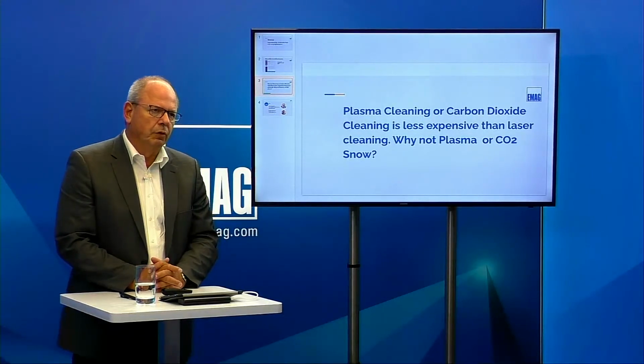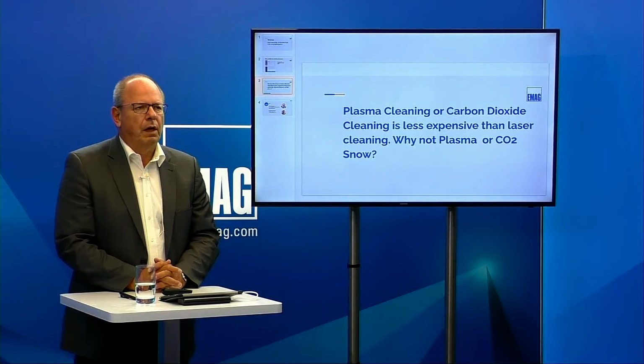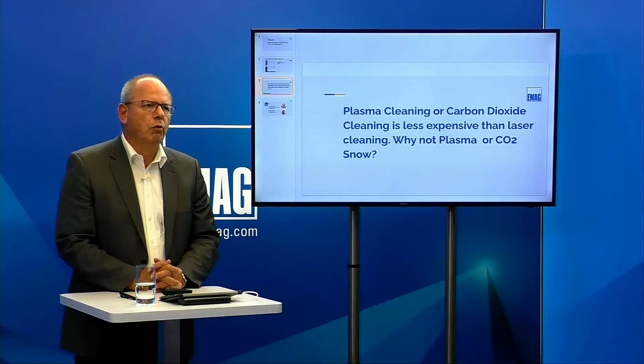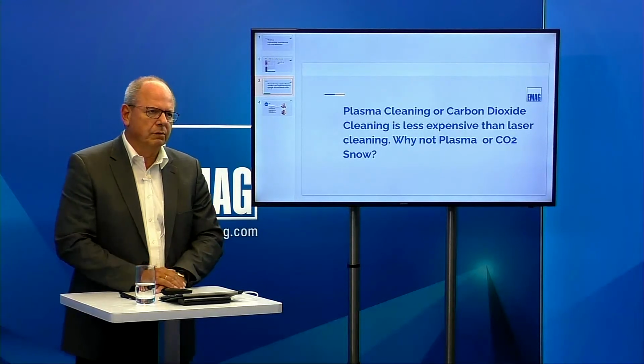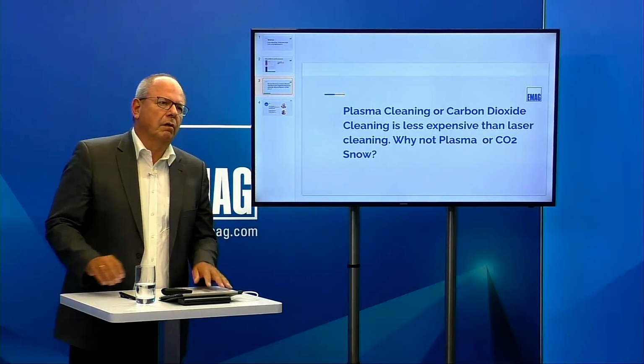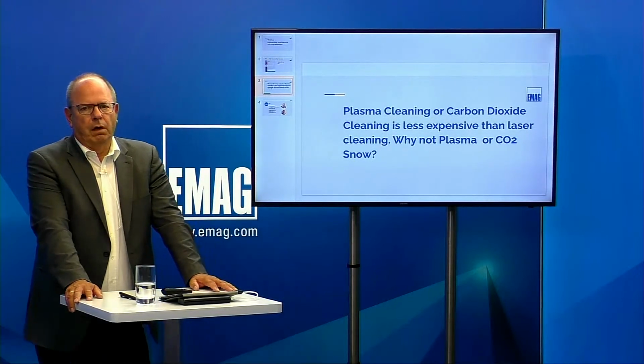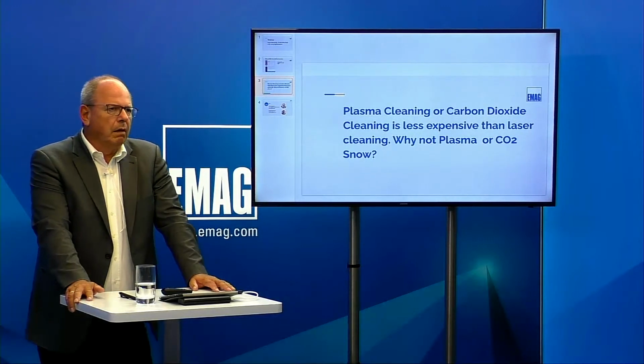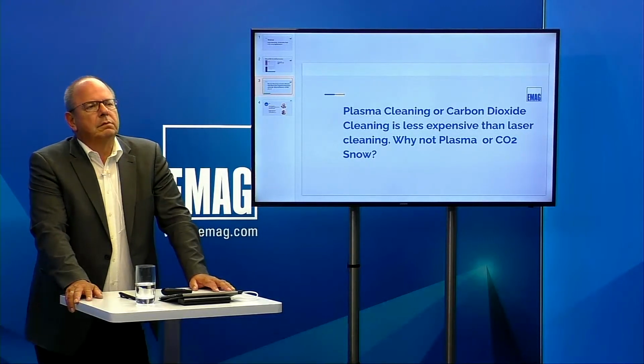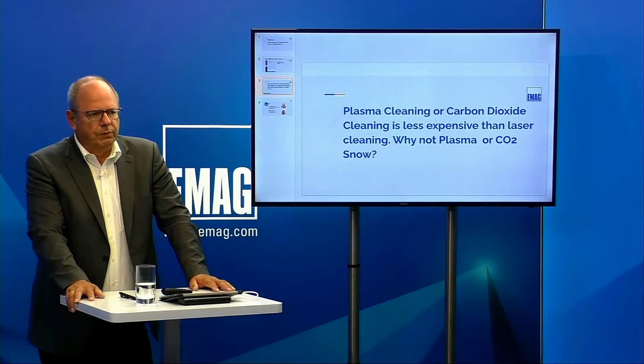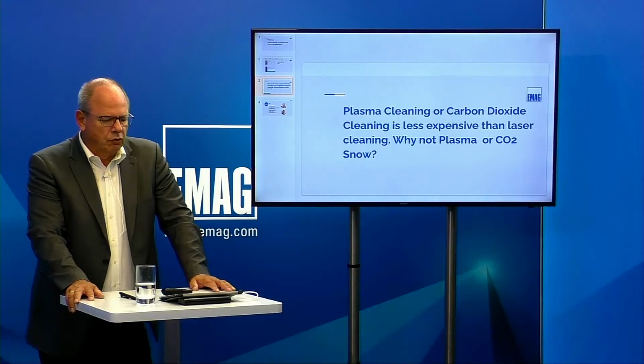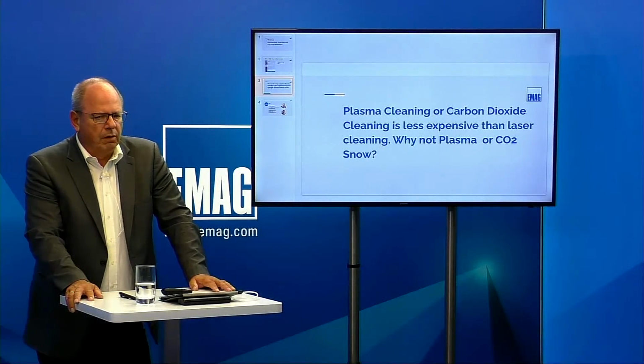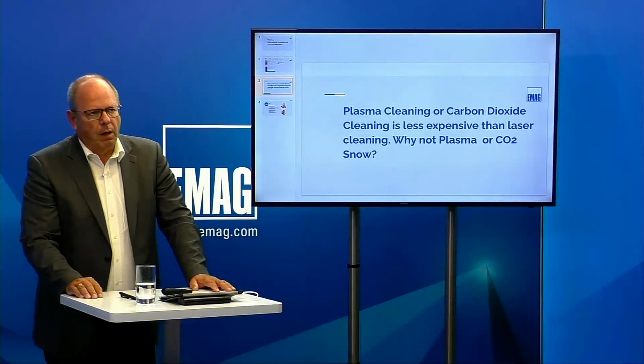So that's good. When we tested this process, we found out it's not so nice if you have, for example, a coolant film or oily films on the workpiece surface. You don't get the quality that is required, let's say, for painting, for gluing, for sealing, for welding. It didn't fit with our quality expectations, so the downstream process was not that good as it should be, and therefore we went away from carbon dioxide snow.